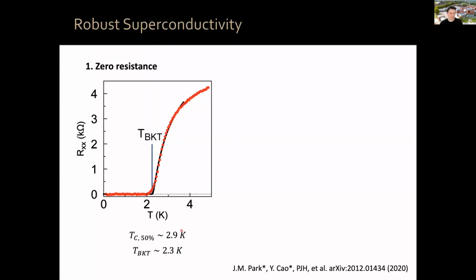Now, these two-dimensional systems, remember, these are the lowest density two-dimensional superconductors that exist. They typically have relatively broad transitions. In the community, we've been mostly quoting the T_C 50% value. I think we are evolving towards this T_BKT, which is a little bit of a more fair assessment of the critical temperature of the systems, because this can be very broad. So sometimes you get artificially high T_Cs. Okay, so zero resistance.